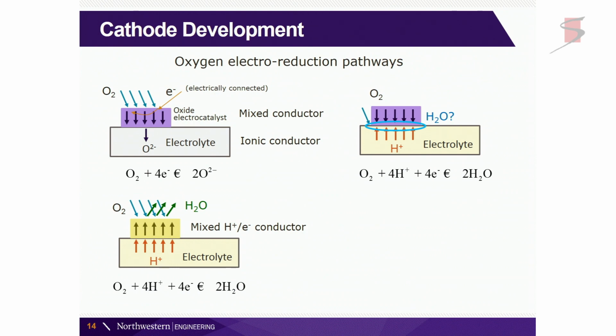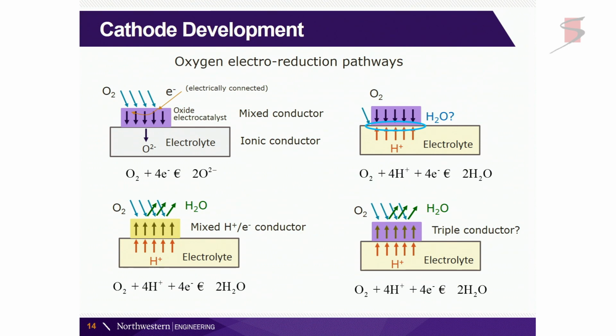So instead, if we look at these traditional oxide electrocatalysts, we know they're oxygen-ion conducting. They would actually be bad news to use because you would start to evolve water right at the interface between the electrolyte and the oxide. That would be bad news. You'd start to delaminate. But there's now evidence that these materials are what are called triple conductors. So in fact, they allow all three ions to move through. And because the protons move through quickly enough, you get electrochemical reaction on the surface. The electrons move to the reaction site quickly and all of that. So this is a great system to be able to develop new cathodes.